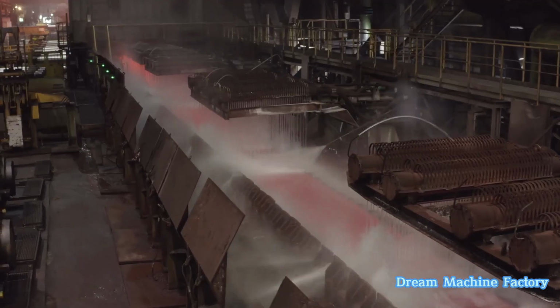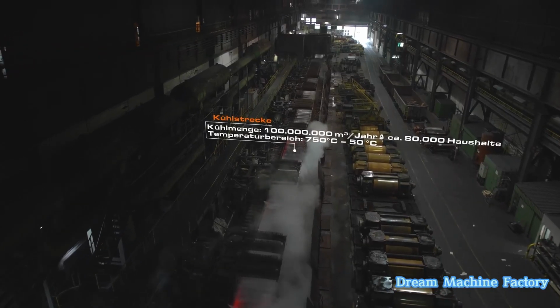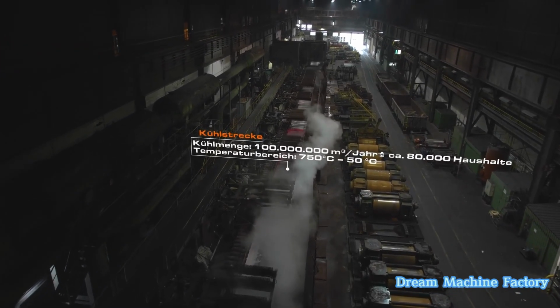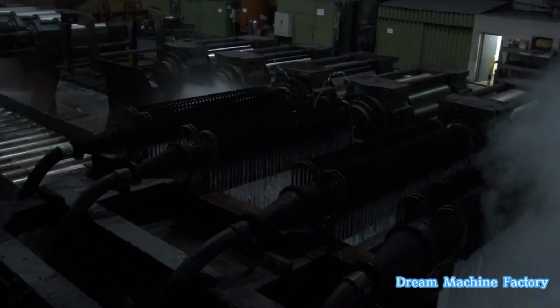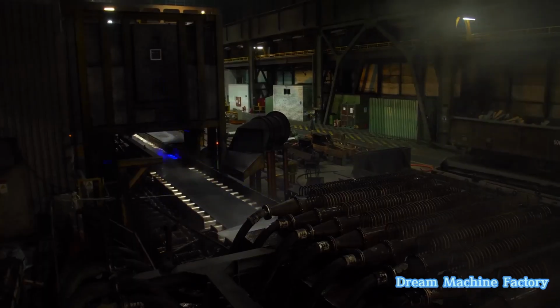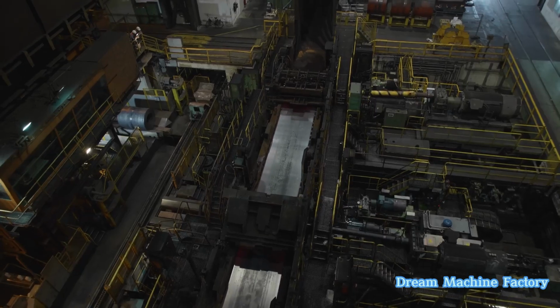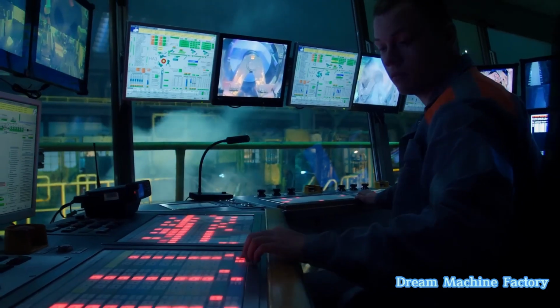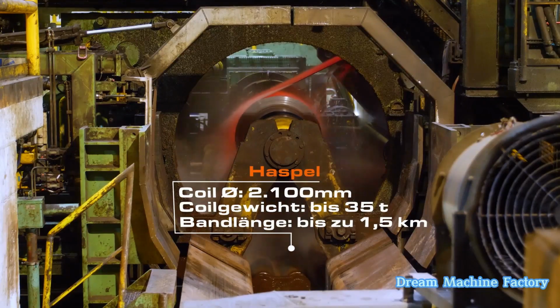to 2,100 millimeters. The cooling system has a capacity of 100 million cubic meters per year, equivalent to the water consumption of 80,000 households. The temperature of the strips is reduced from 750 degrees Celsius to 50 degrees Celsius, ensuring they are ready for coiling.